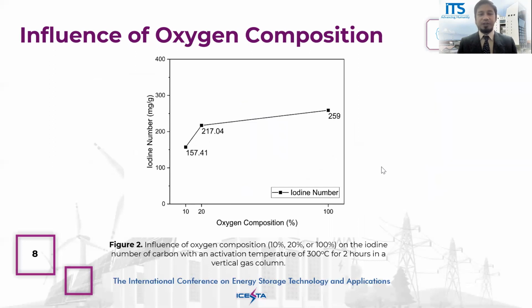On the influence of oxygen composition, the result shows that the higher the oxygen composition, the higher the iodine number of the carbon. The highest iodine number attained was 259 milligrams per gram with an oxygen composition of 100%. The increase in iodine number is due to the development of pores, with increased porosity of the carbon as the decomposition by the oxidizing agent increases.